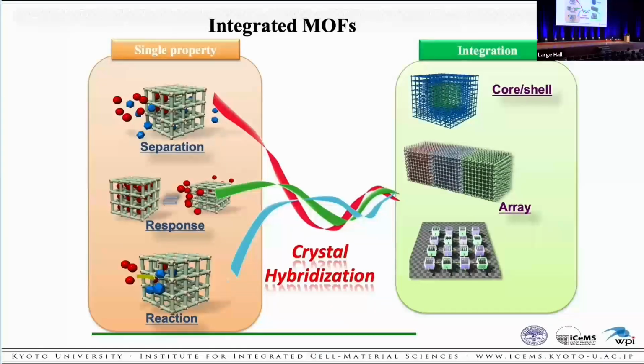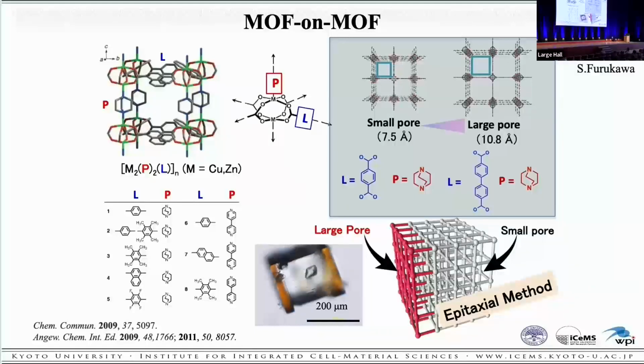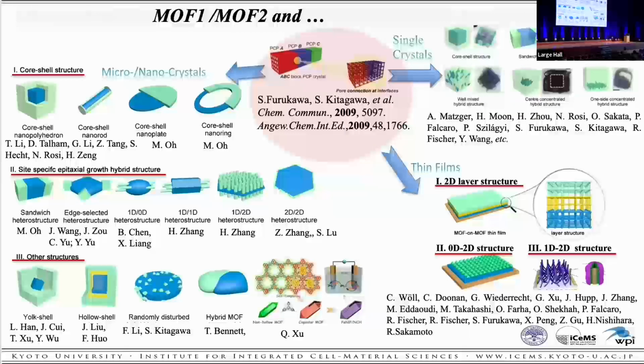I'd like to mention the MOF crystal integration. 12 years ago, we synthesized a core-shell crystal by epitaxial growth of two crystals, one with small pores and the other with large pores. As you can see here, the outer one was size selective, and the inner one was capable of massive storage. Nowadays, a wide variety of MOF crystal composites have been synthesized, as shown here. There is no time to talk about each application, but the numerous possible applications show the development of MOF chemistry is progressing rapidly.